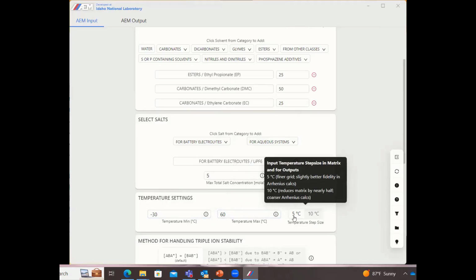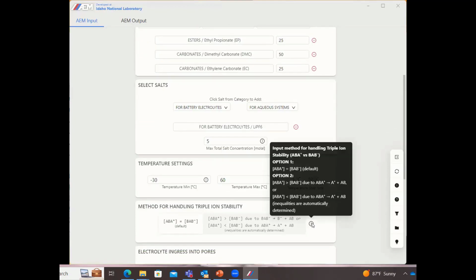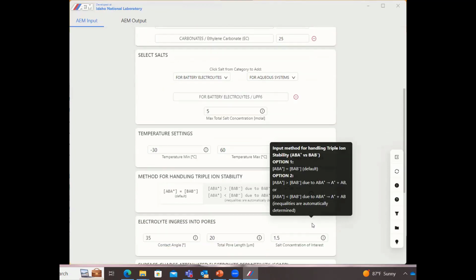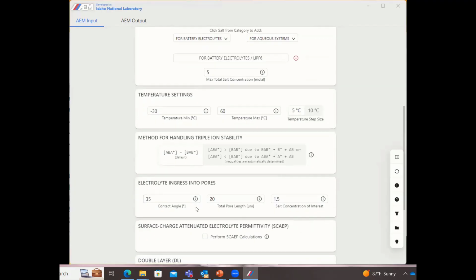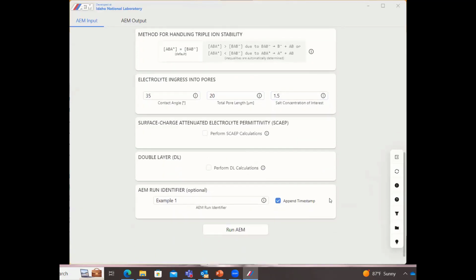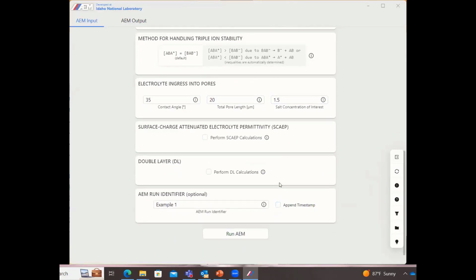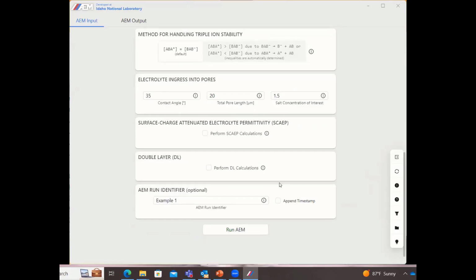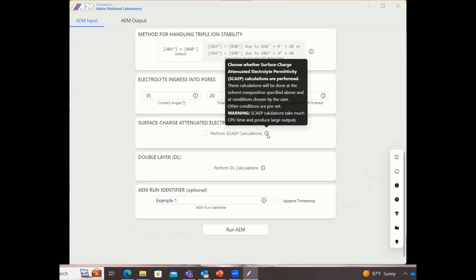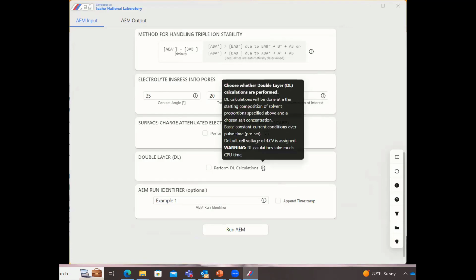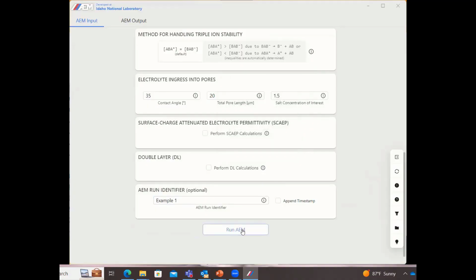For the method for handling triple ion stability, we'll use the default settings for that. And then the electrolyte ingress into pores, we'll use a contact angle of 35, a total pore length of 20 microns, and then the salt concentration of interest of 1.5. And at this point, we have entered all of the simulation conditions for example 1, but the program also supports the ability for surface charge, attenuated electrolyte permittivity, and then double layer calculations as well. So here we are running the software program, and it should be completed momentarily.